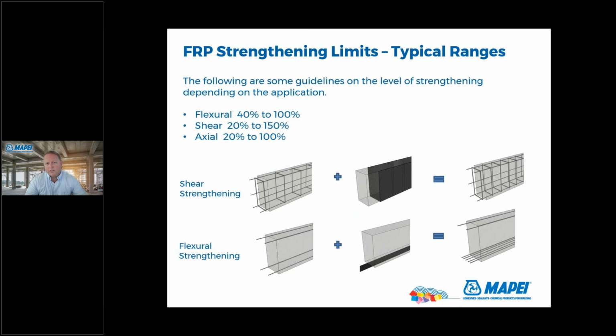So this is just some strengthening limits, typical ranges. Every project's different depending on the size of your member and the reinforcing that's in there. But for flexural, you're going to be looking at a range between 40 to 100% increase in the strength. Shear 20 to 150, and then axial about 20 to 100% increase. These pictures just kind of show you the existing reinforcing. You add some FRP. It's similar to if you had a tighter spacing on your bars or more bars in there.